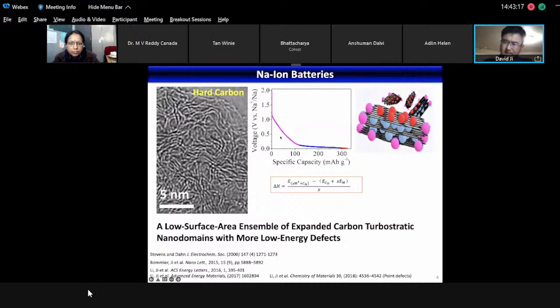We all know that graphite probably doesn't do the job for sodium ion storage. It's not just graphite's fault. It's the combination of the binding energy between sodium ions and graphene layers, and also the relatively large cohesive energy of sodium metal. The difference between the metal term and the carbon-sodium binding energy term is not negative, so you don't have a positive voltage for the half cell. I'm just using enthalpy here to represent the free energy change because the entropic change is pretty minimal. All right, that's the first insight I hope to share.